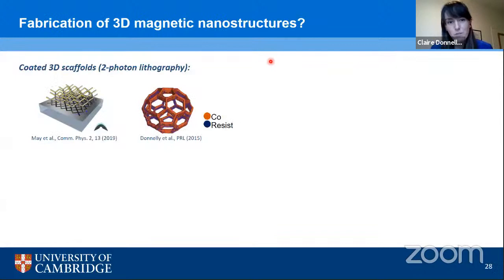So what's been done so far? Well, there's been a couple of main ways in which 3D printing, essentially, of magnetic materials has been achieved. And the first is through the coating of non-magnetic three-dimensional scaffolds that can be realized with techniques such as two-photon lithography. And in this way, this has led to the realization of, for example, three-dimensional artificial spin ice lattices, or geometrical structures such as this magnetic buckyball.